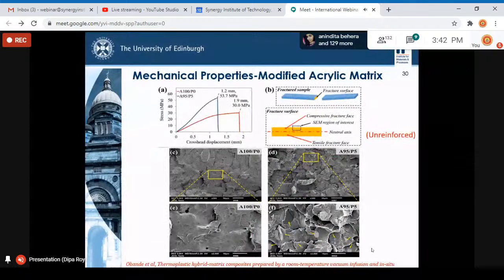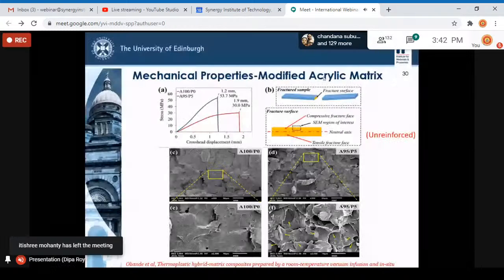We selected one blend with 5% polyphenylene ether, and we did some very preliminary mechanical testing with the unreinforced matrix. These are not composites, these are unreinforced modified acrylic matrix. With some simple flexural testing, we saw a significant enhancement in this blended material. So this is the strength, sorry. Even with 5% of polyphenylene ether, the strength increased significantly from 30 to about 54 MPa. So this was a good indication that we are going to see some enhancement in the mechanical properties as well.